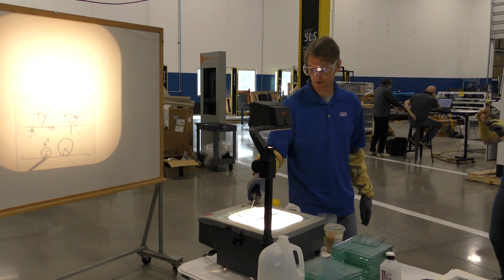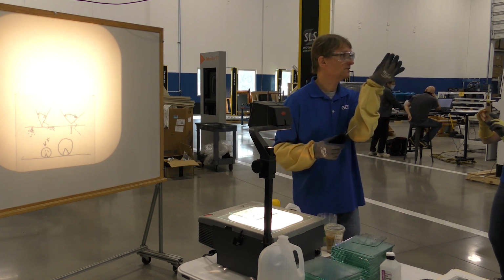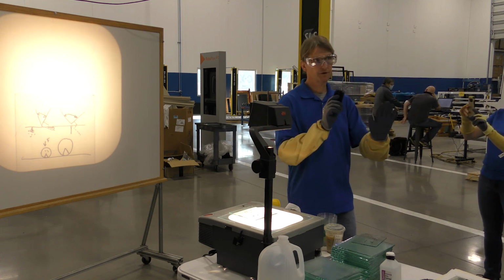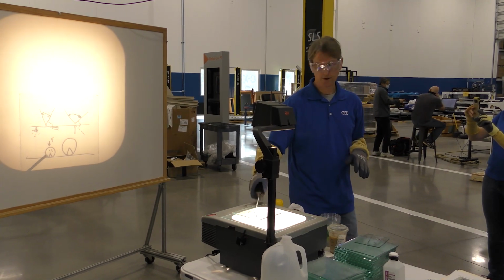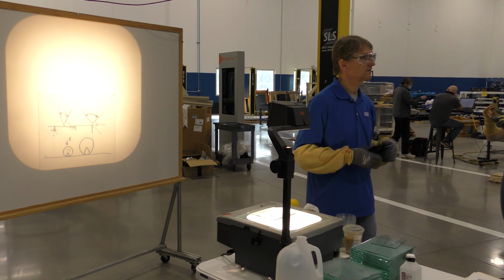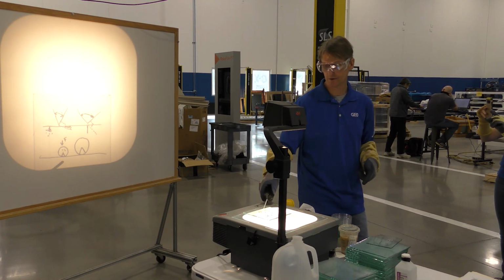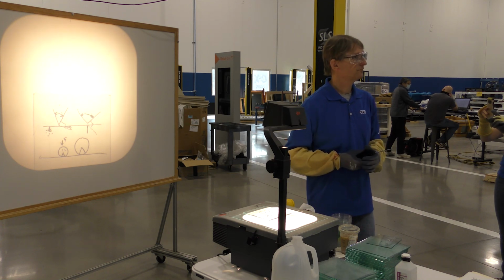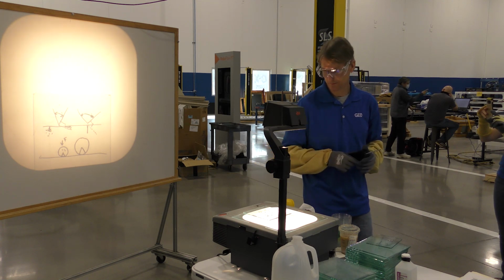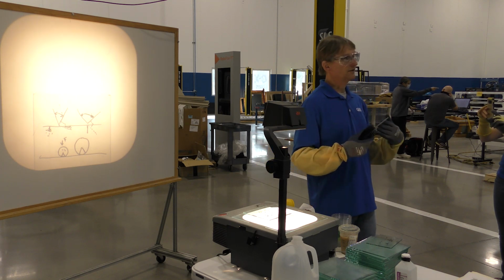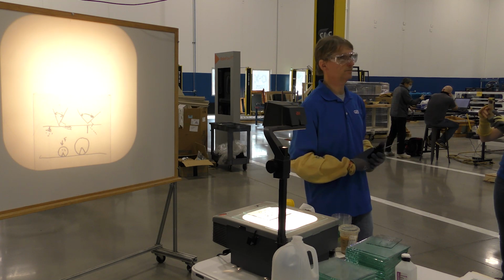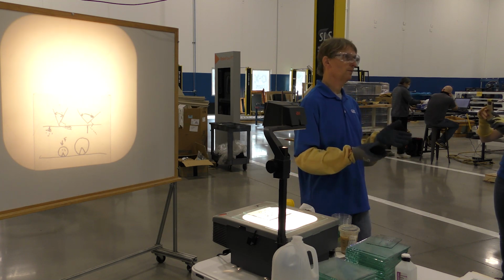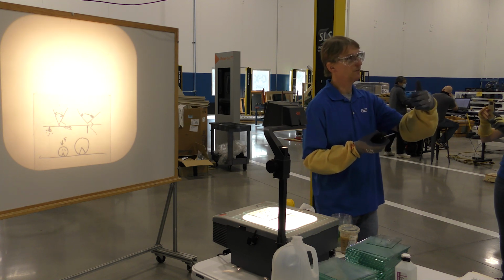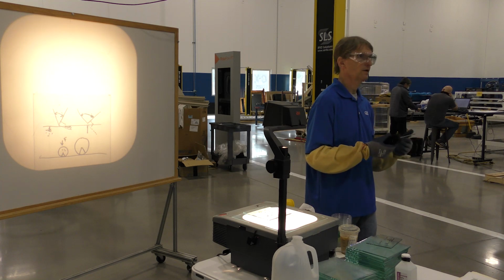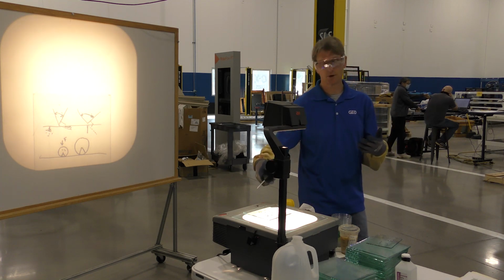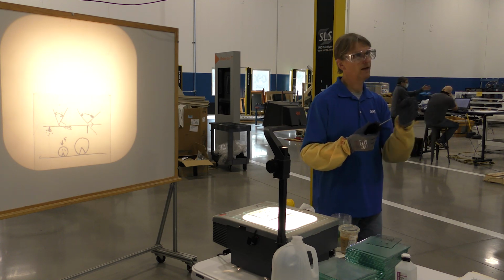So a smaller diameter wheel is a sharper bite into the glass and I need less force. There are a couple of pros and cons to this. A smaller diameter wheel for the same linear distance has a lot more revolutions, so it's going to wear faster than a larger wheel. A larger wheel is not going to be so good at cutting arcs and shapes as a smaller wheel. A smaller diameter wheel is going to go around a tight radius much better. If you're making something with a 2-inch or small radius, a large diameter wheel is going to plow as it goes around and make that turn.